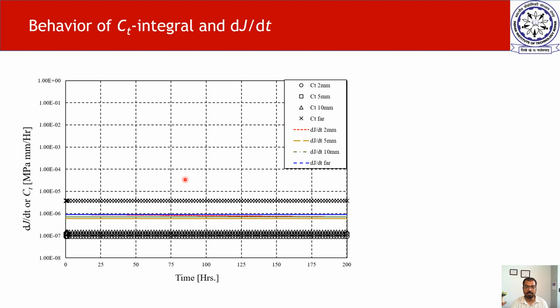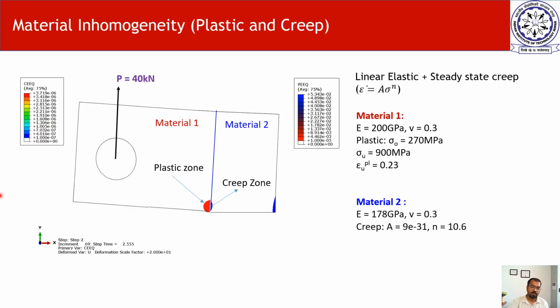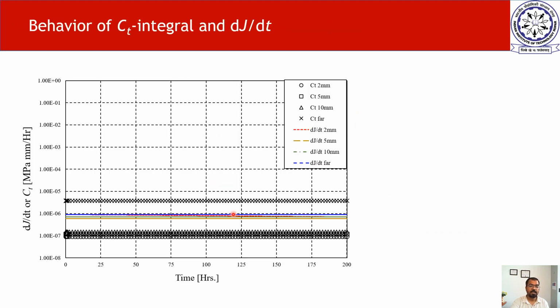One can calculate by one's own code by taking the plastic strain also into account. But J integral is taking everything into account. So it is also taking this plasticity. It is also taking this creep deformation on both sides of the interface at the crack tip, and that shows a better representation of the crack driving force, and it also shows better path independence even for the far field integral for 2 mm, 5 mm, 10 mm far field integral.